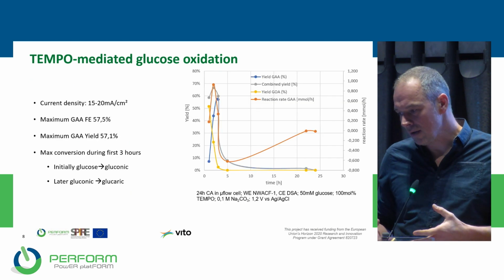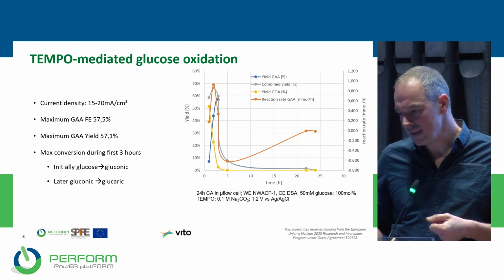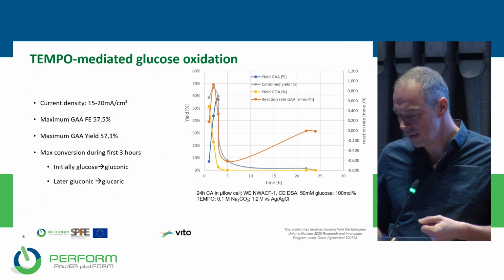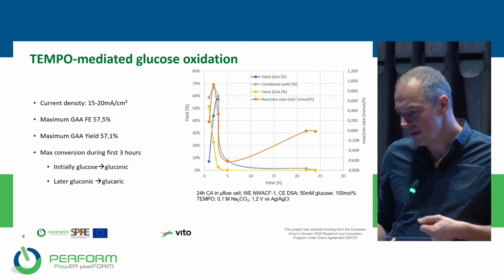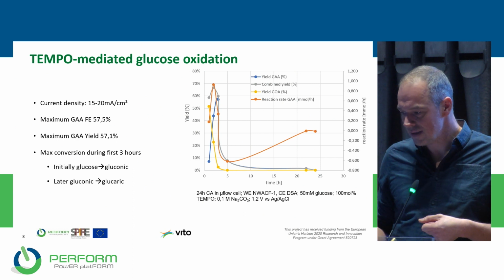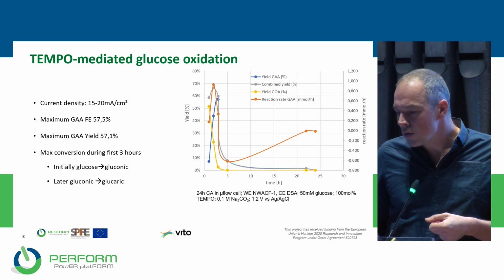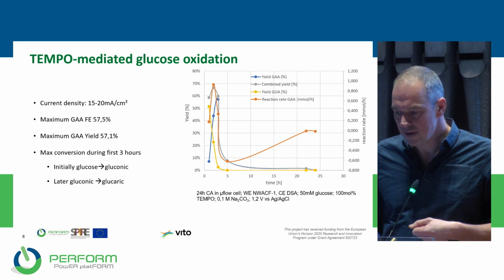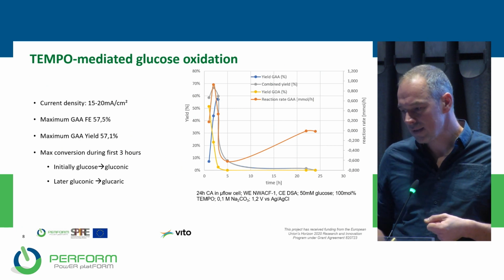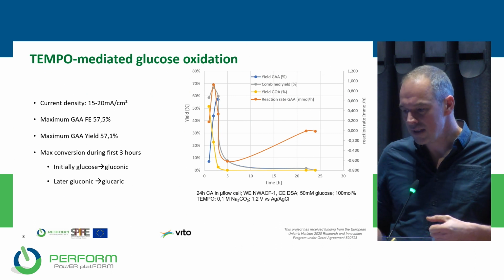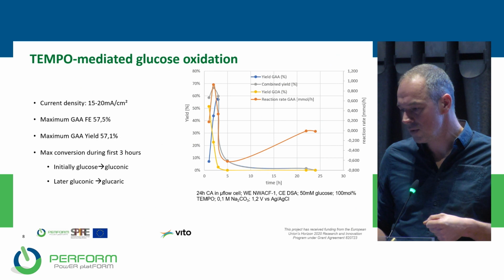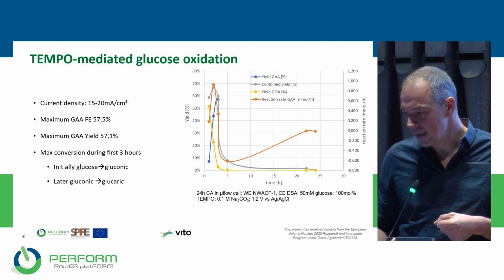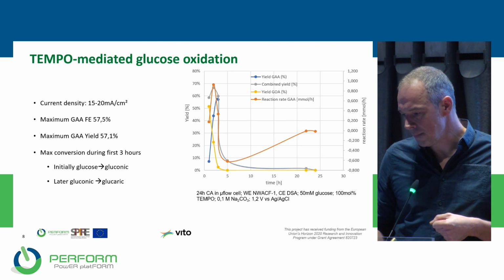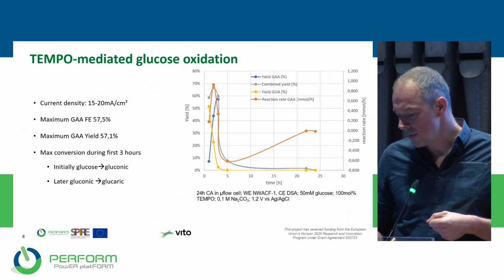When we did a longer-term experiment during chronoamperometry, so we operated the cell at fixed potential, we saw that we could achieve a Faradaic efficiency towards glucaric acid of around 57.5%, almost 60%, and the same for the yield. So we could convert 60% of the glucose to glucaric acid, which was extremely nice at that time. So this was done during a 24-hour experiment.